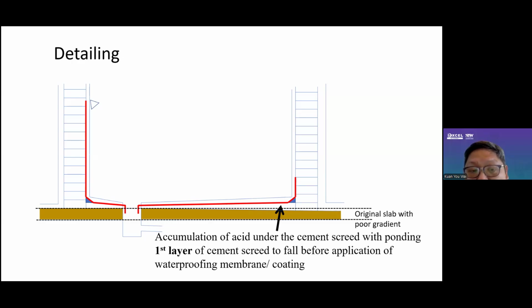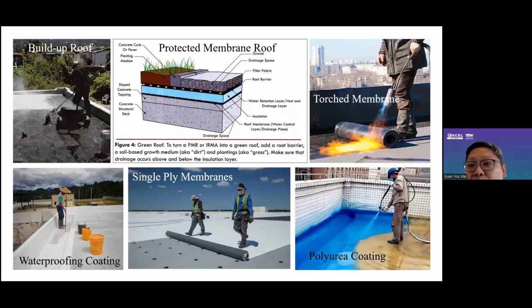So as a result, it is very important to have cement screed to fall so that our waterproof sits on the cement screed at a gradient. No water puddle or accumulation of acid can happen if we do a layer of cement screed to fall before we apply the waterproof. So, okay, I would like to show you how the build-up roof looks.